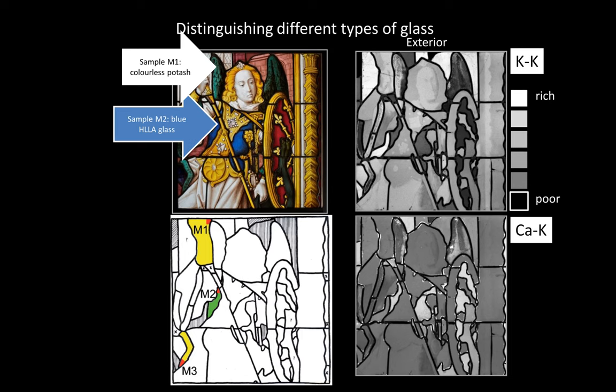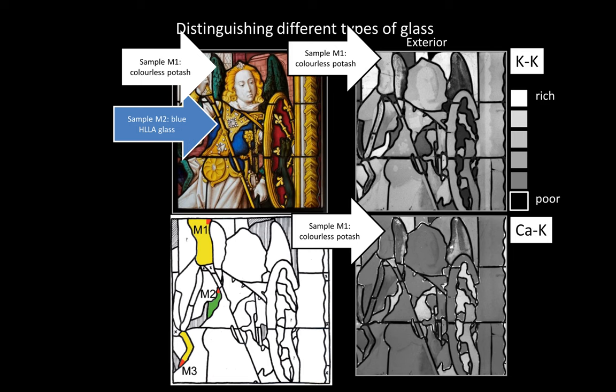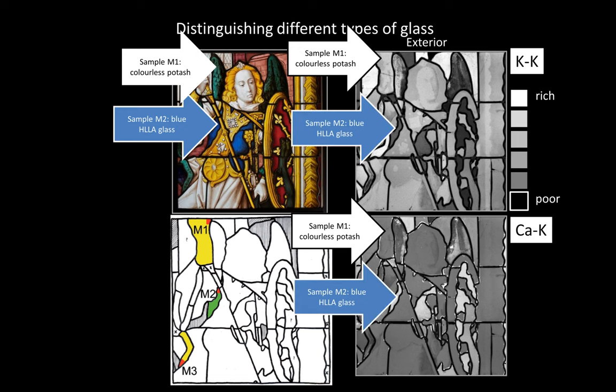Looking at the distribution of calcium and potassium, we clearly see differences in intensities between the different pieces of glass. The colorless potash glass, from which sample one was extracted, seems to yield a relatively high potassium intensity — relatively white in the image — while other pieces are poor in potassium and look dark or black in the image. The blue high-lime, low-alkali sample is indeed taken from a glass piece rich in calcium. So the distribution images do seem to make sense. However, we need a better and more statistical way of looking at this data.